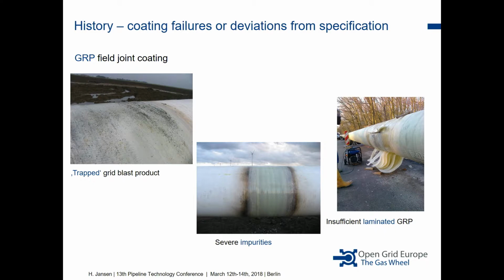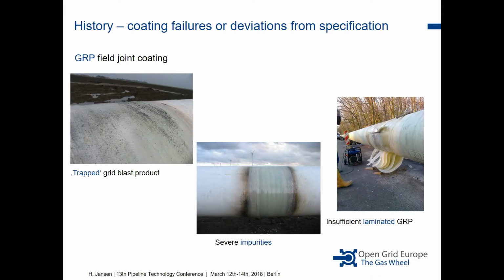And what happened here? You may imagine that the first staff was doing the surface preparation with sandblasting, and the coating team was preparing the glass fiber epoxy and laminating the system, and the wind carried the grit blast from one field joint to the one that was just under preparation, and it got trapped in the epoxy compound. If you see this, there was mud that was laminated in the GRP field joint coating,